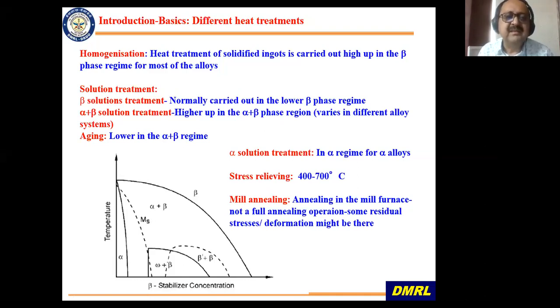Then solution treatment, there are several of them. The two that are very commonly used, one is beta solution treatment. In beta solution treatment, what you do is you take the alloy to this beta regime just slightly above. You do not want to take it too high, because you see the BCC structure is a very open structure and diffusivities are very high. So there can be very large grain growth if you take it to too high a temperature or keep it for a longer time. So you have to be careful. You have to do a shorter time. But the beta solution treatment is just done above the beta transus, maybe maximum 50 to 100 degrees centigrade above the beta transus of the alloy.